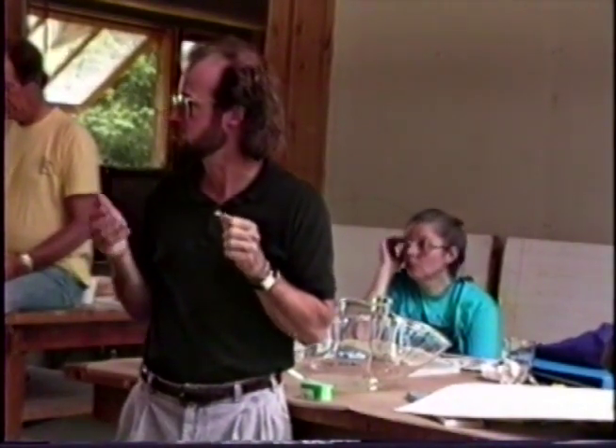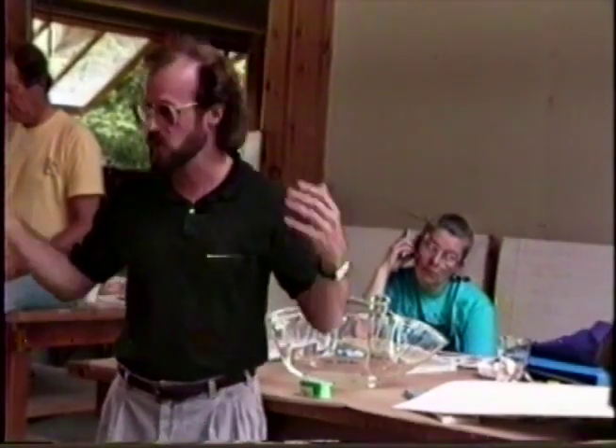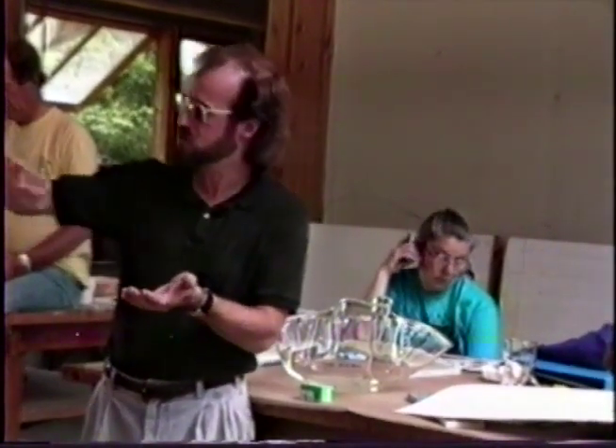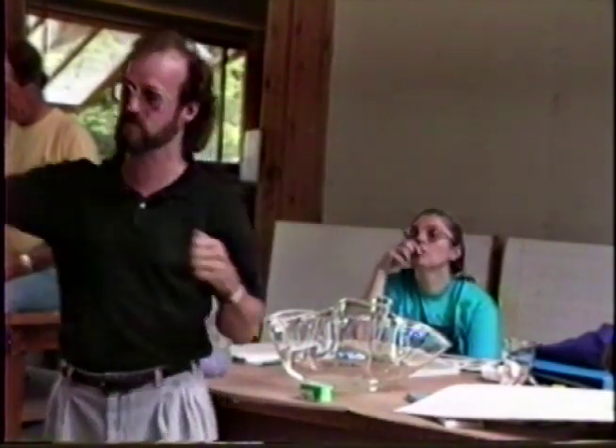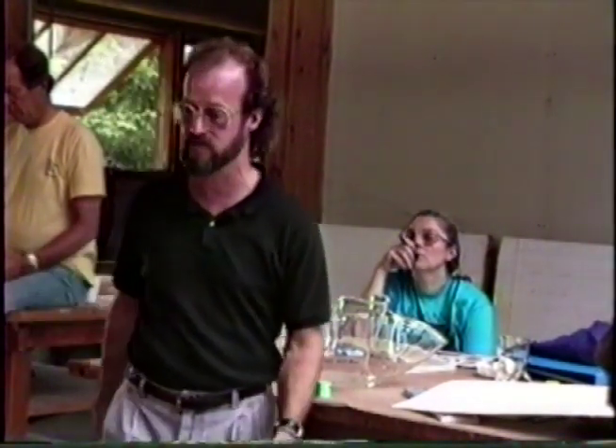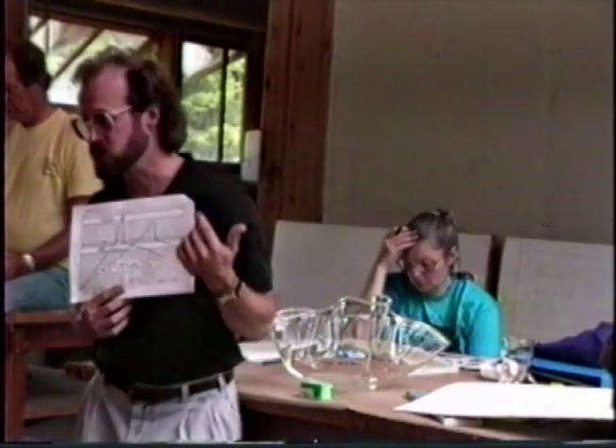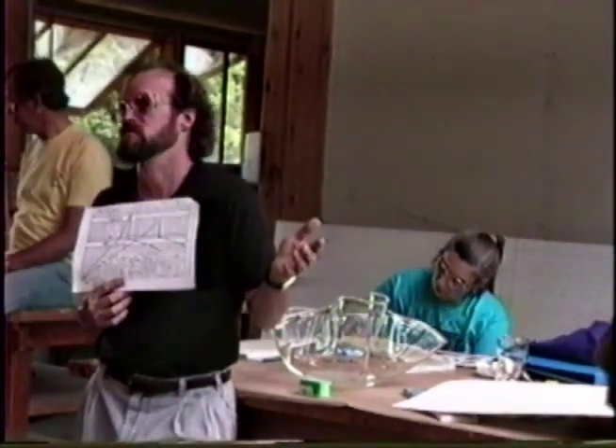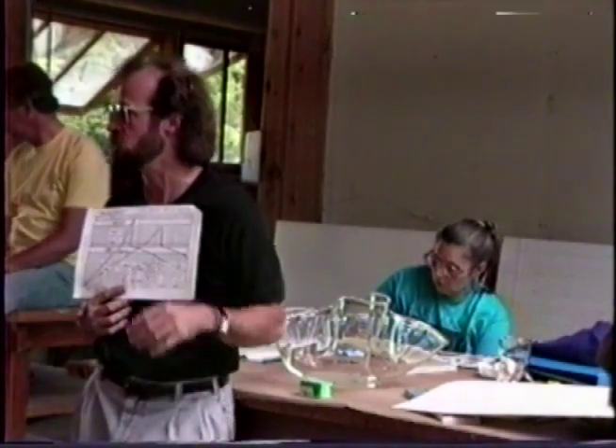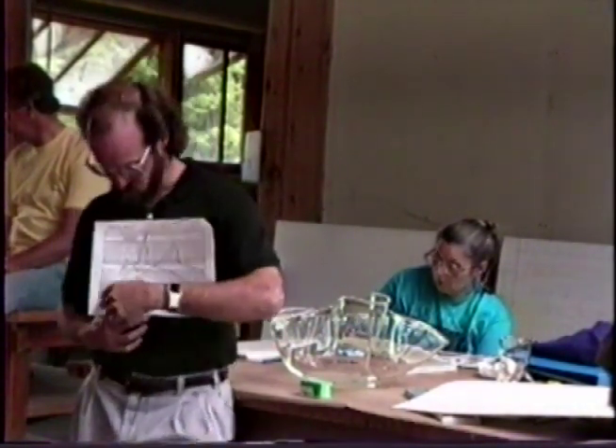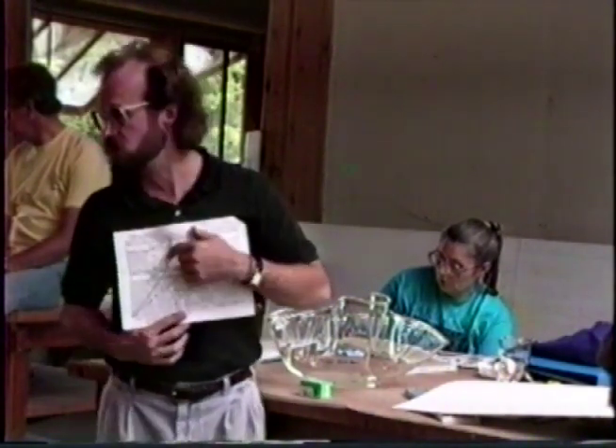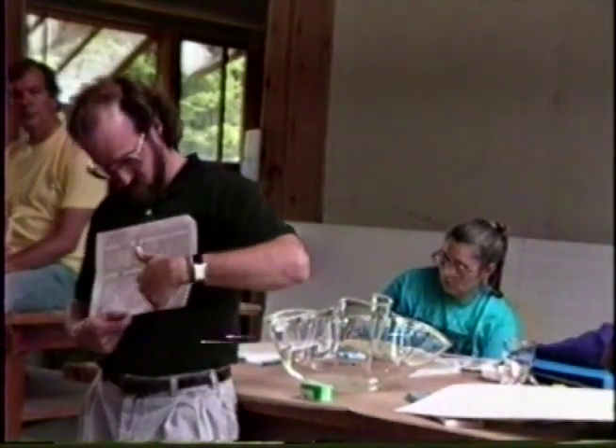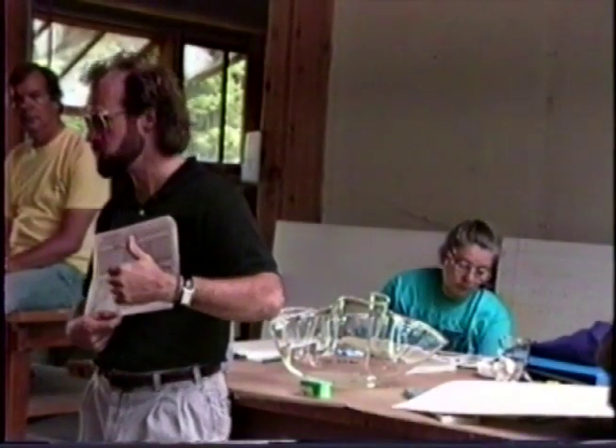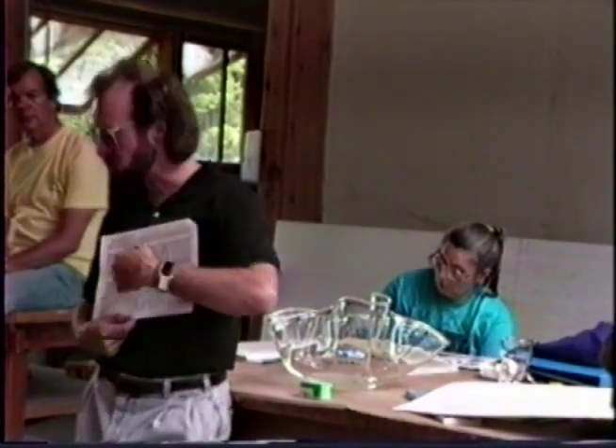The reason is the top surface of the glass starts expanding as it heats up, and the inside's just not moving. So you have to take the glass up at a relatively slow rise, slow enough so that the outside surface and the inside will expand at roughly the same rate. If one's moving more than the other, there's a certain point where the stresses build up and it'll crack the glass. That's called thermal shock. So the thermal shock zone is roughly 300 to 800 degrees. It's really the critical point, up and down. So you need to fire your kiln fairly slowly, and with a top firing kiln, I figured 2 hours to 1,000.